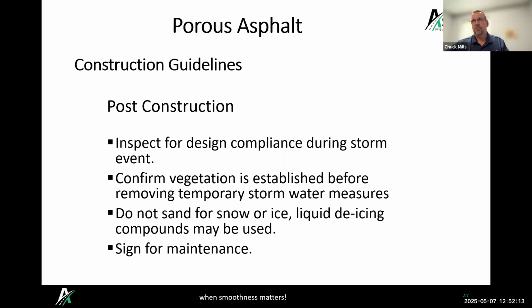So kind of the best practice is if you're plowing that, you want to keep your blade up on the porous so that you're not scarring it or scuffing it or anything like that. But we find that any small buildup of ice or snow really melts really fast, mainly because the water can't just puddle on top of the surface there. As soon as it starts to melt, it goes right down into the porous system.